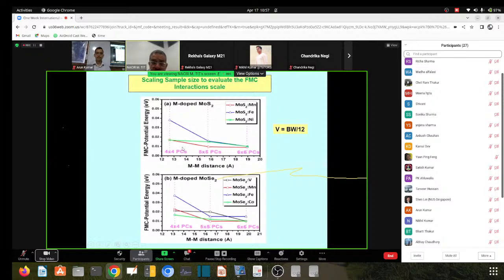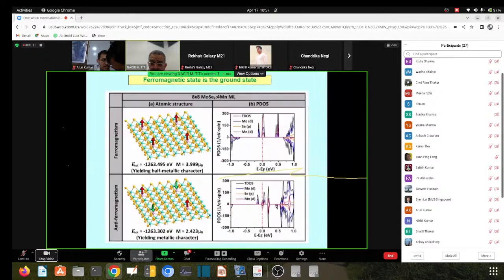Here I plotted it versus 3 dopants in the case of MoS2, where we said it's manganese, iron and nickel. And this yields the half metallicity. In MoSe2 we have four dopants: vanadium, manganese, iron, cobalt. And we show the samples 4x4, 5x5, and 6x6. So the V is reducing, and probably at 7x7 we don't find any interaction. So we could estimate the scale of the ferromagnetic interaction.